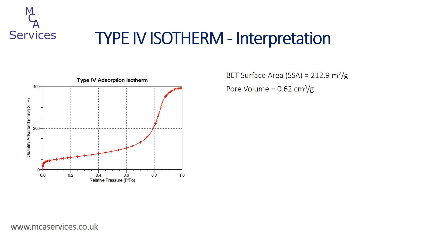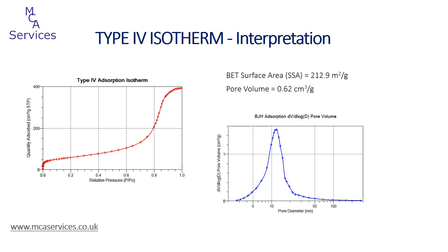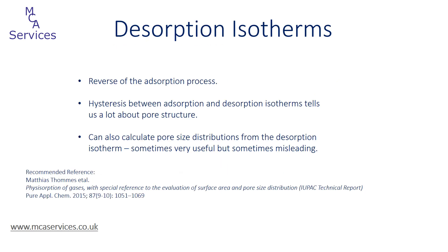Finally, we can characterize the mesopore size distribution because the pores are completely filled with adsorbate and will become fully resolved, unlike the type 2 isotherm. We have applied the BJH model — the Barrett-Joyner-Halenda method — to the adsorption isotherm, and this plot shows the log differential pore size. The pore sizes within the sample range between 2 and 50 nanometers in diameter, with the majority of the distribution in the range 2 to 25 nanometers and the average D50 size calculated at 10.2 nanometers. It's more common to measure both adsorption and desorption isotherms to maximize the information derived from this analytical technique.